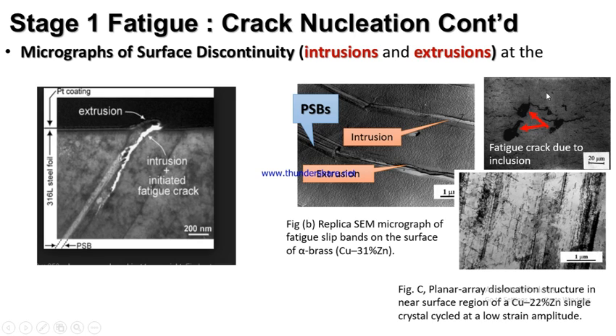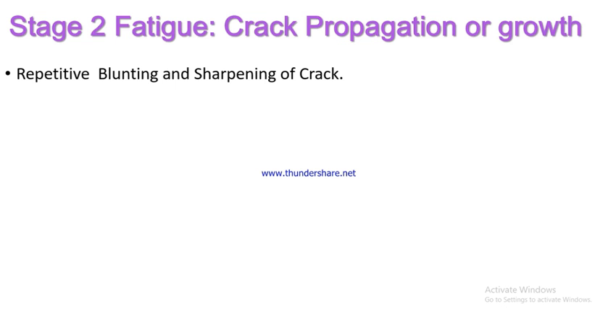And when these materials are subjected to cyclic loading over a long period of time, this stress field will definitely lead to local yielding, which can initiate cracks, and the cracks will begin to grow and propagate to final fracture, which can cause fatigue. Okay.